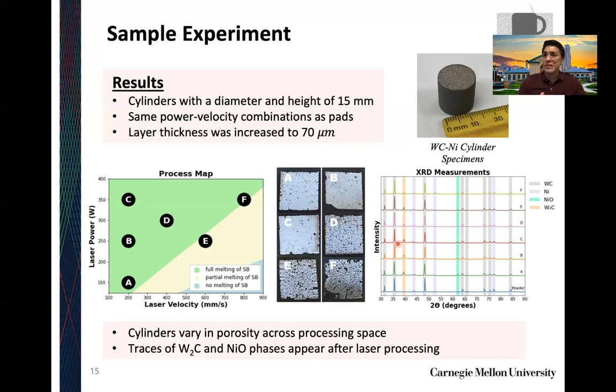We also did a chemical analysis using XRD on all our parts, but I'm only showing you these 6. You can compare that to the standard powder, which is the raw material before laser processing. So a couple things to note. These gray vertical bands all show tungsten carbide peaks, which are present in all of our samples, which is great. The purple bands, which is this band here, and this band here, are our nickel peaks, which are present in all our samples. Great again.